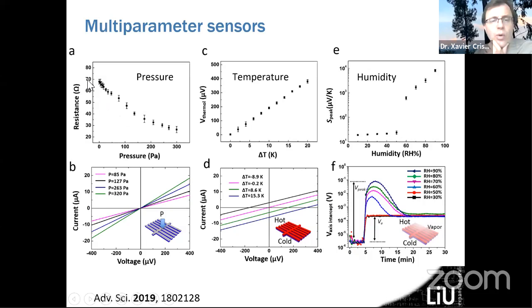As we have seen before, when you apply a pressure to the material, the aerogel decreases in size and the resistance decreases. That gives a change of slope, as we mentioned before. I also told you about the effect of temperature: when you apply a temperature gradient to the aerogel, there is a voltage developed due to the Seebeck effect of the electronic charge carriers, and it appears as a shift in the IV curve - they are shifted like this.